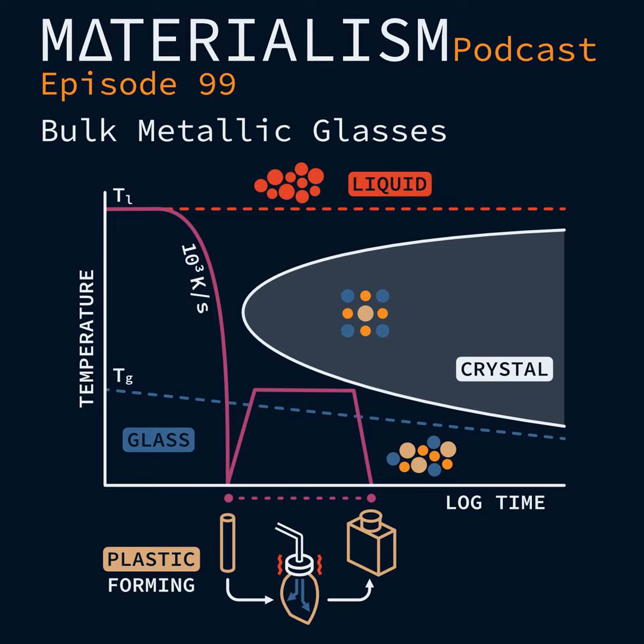So to remind you of steels, that's why they put manganese into steels. I learned this from your podcast, right? You put manganese into steel to scavenge the sulfur, which otherwise would cause a lot of problems. And so there are similar strategies. We, for example, use yttrium to add into the alloy, and yttrium likes oxygen a lot more than zirconium, titanium, nickel, copper, and all these other elements. So that is a very, very valuable strategy.